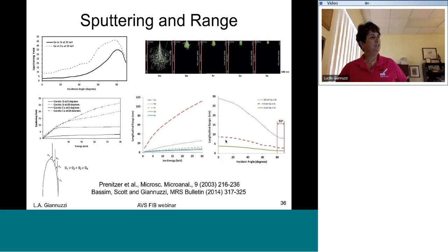So if we take a look at sputter yield now, and how different things sputter, there's a lot going on here. Let's start with this upper right area here, which I showed you previously. This showed that you're going to get very different ion-solid interactions for different ions in the same material, same energy. Okay, we look at sputter yield versus incident angle. For 2 different materials, we see, first of all, that the sputter yield of copper for gallium in copper is about 2.5 to 3 times larger than for gallium in silicon at 30 kV. It reaches a peak, and we see that we get very, very fast milling at the surface. So what we're going to try to do when we do specimen preparation is always mill at a grazing angle to the surface, because this is going to generate our fastest milling.